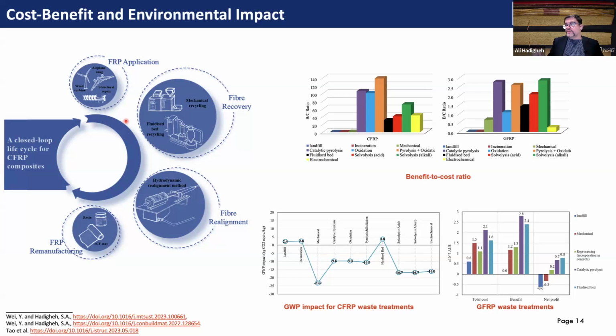We looked at both CFRP and GFRP, carbon FRP and glass FRP, and because the scenario is different, the recycling method would be different for carbon and glass composite. GFRP is quite cheap, and you can't use energy intensive or very expensive methods for recycling the glass fiber from GFRP. But for CFRP, it makes sense because it is a strategic material, it is expensive, and production of virgin carbon fiber is very energy intensive. So it makes sense to use pyrolysis or solvolysis process for extracting carbon fiber from FRP. So we looked at these methods.